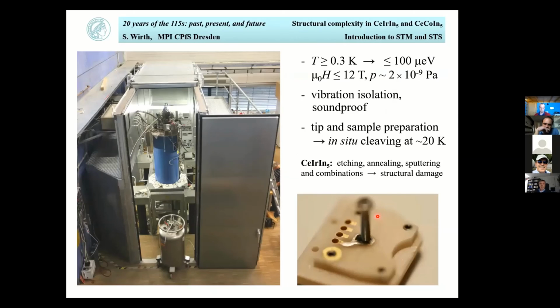Now let's go to the STM. Some of you have seen my STM. It's a low temperature STM going down to 0.3 Kelvin. But what's important is we have an in situ cleaving stage, so we cleave at about 20 Kelvin. I should point out that I put in quite some effort with other techniques, because cleaving is actually a pretty high energy thing. You knock off the whole thing. You see here an M1 screw glued on top of our sample, and that's then knocked off in situ. But if you do anything else, at least I was not successful.